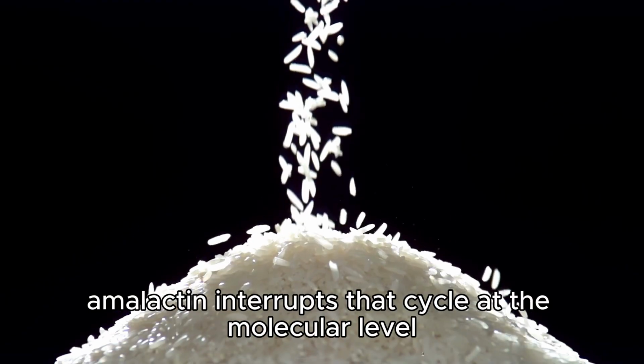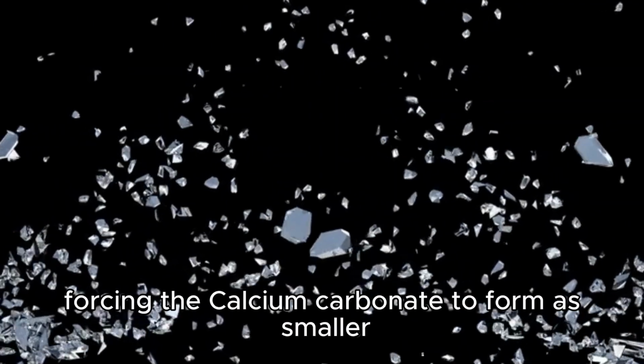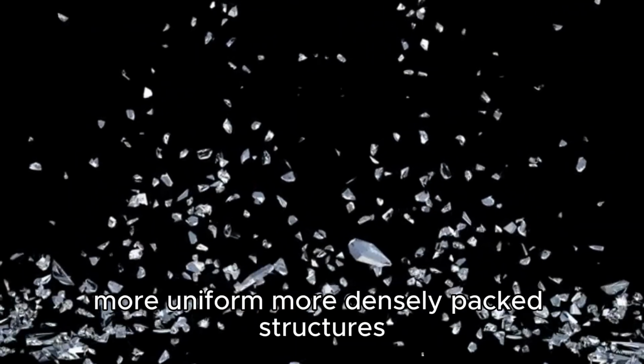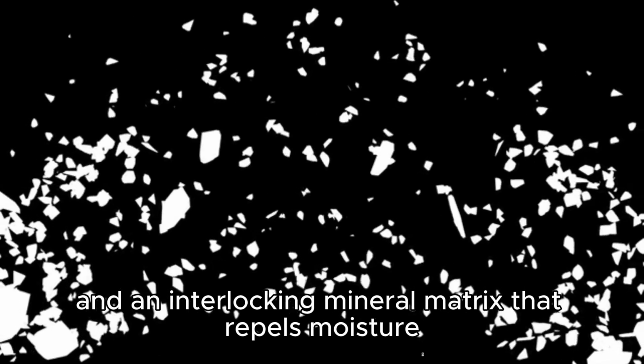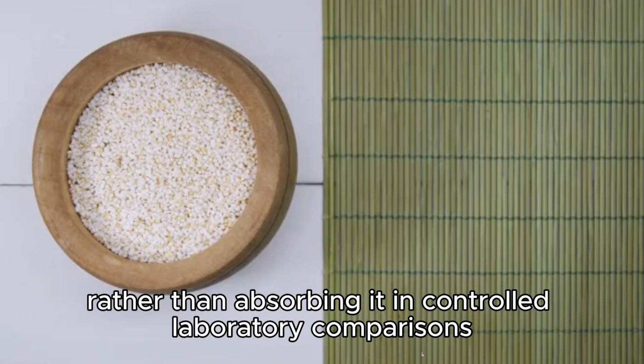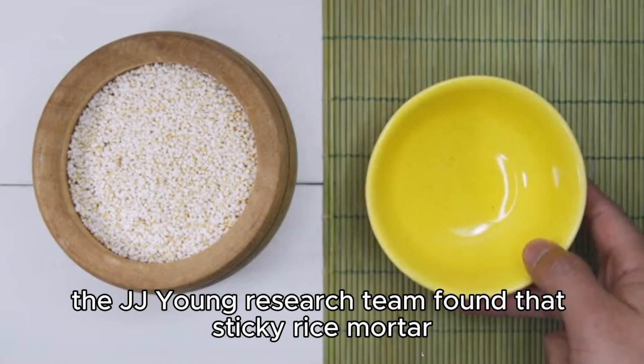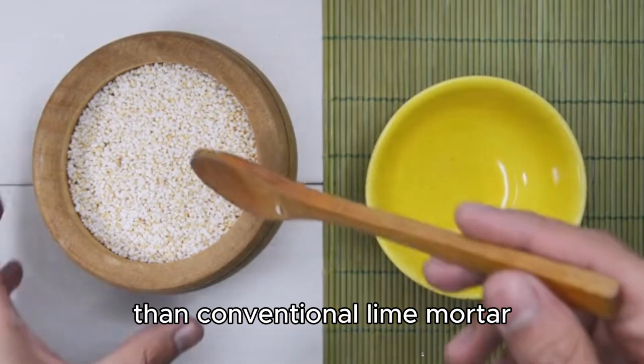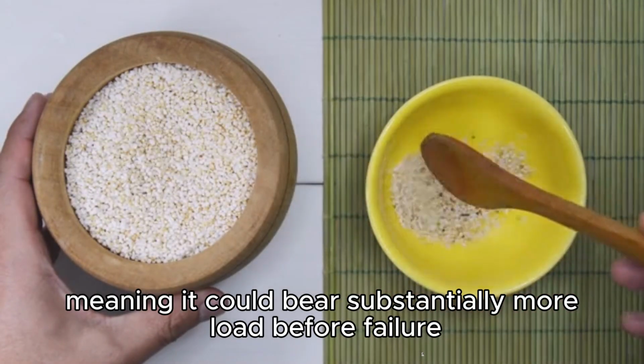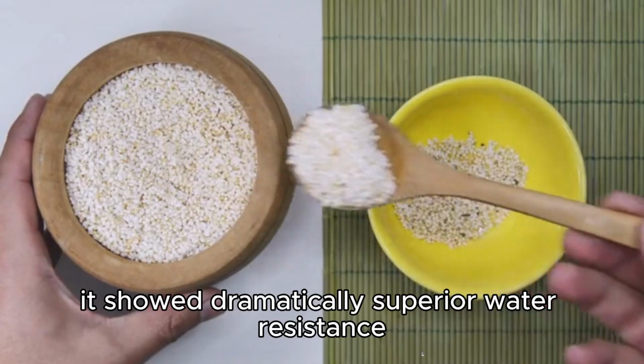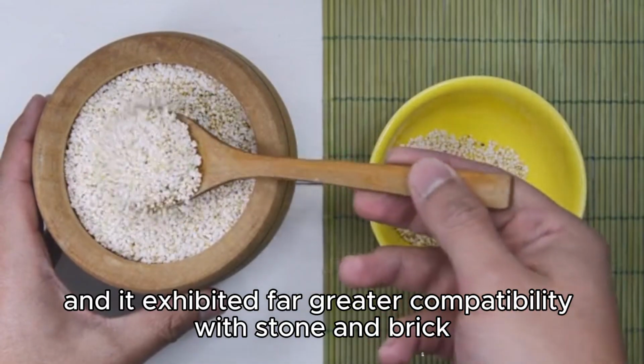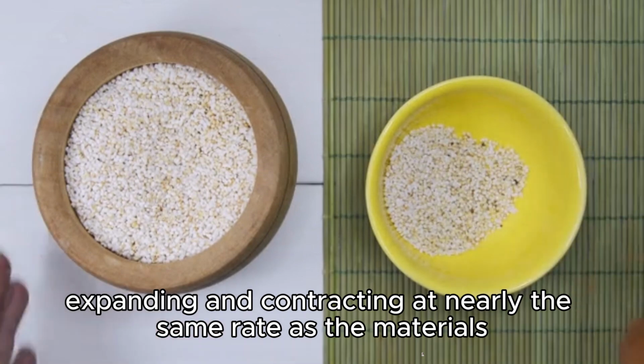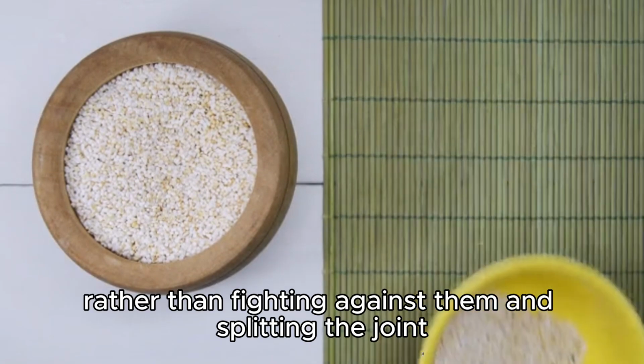Amylopectin interrupts that cycle at the molecular level. It constrains crystal growth, forcing the calcium carbonate to form as smaller, more uniform, more densely packed structures. The resulting microstructure is dramatically tighter than anything standard lime mortar produces on its own. There are fewer voids, almost no open pathways for water, and an interlocking mineral matrix that repels moisture rather than absorbing it. In controlled laboratory comparisons, the Zhejiang research team found that sticky rice mortar demonstrated significantly greater compressive strength than conventional lime mortar, meaning it could bear substantially more load before failure. It showed dramatically superior water resistance, and it exhibited far greater compatibility with stone and brick, expanding and contracting at nearly the same rate as the materials it was bonding, rather than fighting against them and splitting the joint.